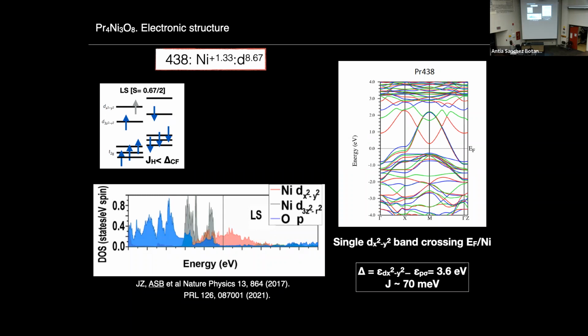So remember, for this material, what we have is an average nickel valence of 1.33+. That's, again, 8.67 d electrons. What we found, once again, using density functional theory, is that in this material, the nickels are happy being in a low spin state, and you can completely forget about what that means. Effectively, what that translates into is that you have, once again, just a single dx squared minus y squared band per nickel crossing the Fermi level. You have here 3 nickels, so just 3 bands, while now the rare earth states are actually higher in energy. They are these guys here. They don't cross the Fermi level anymore.